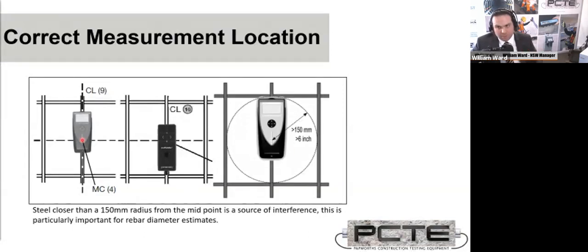The other point on this slide is that we consider the electromagnetic field on a cover meter to be around 150 millimeters from that center probe in all directions. So if you have additional reinforcing steel or other metal close to your measurement point within that 150 mm sphere, you will need to use some form of adjustment to correctly measure. If it's a simple geometric correction, you would be able to use neighboring rebar correction. If it's a more complex layout, the Profometer in particular offers you some calibration settings you can adjust.